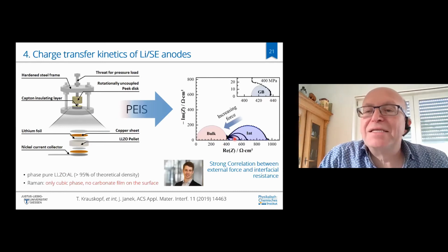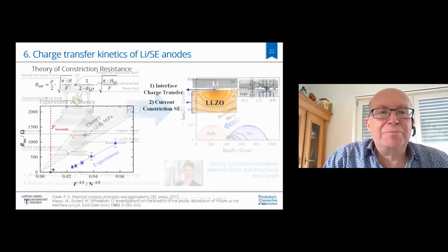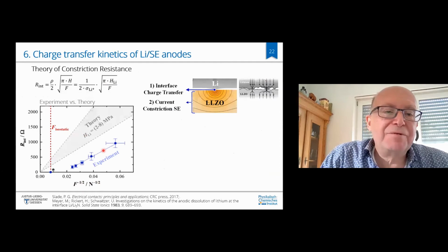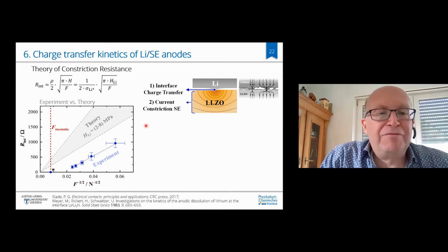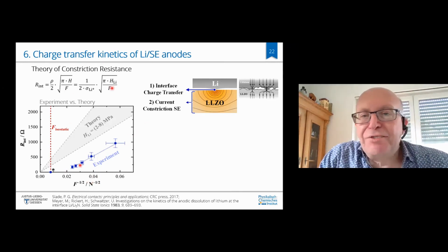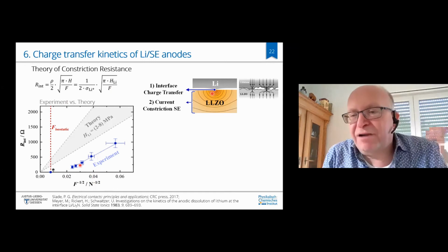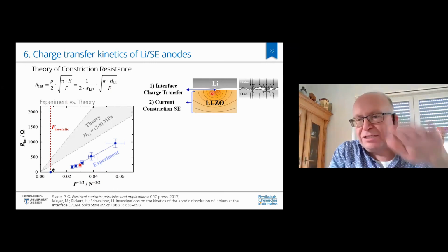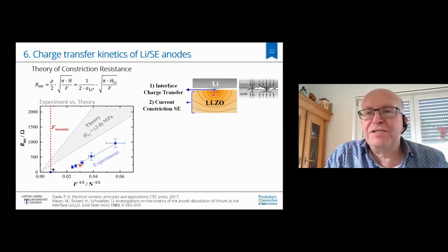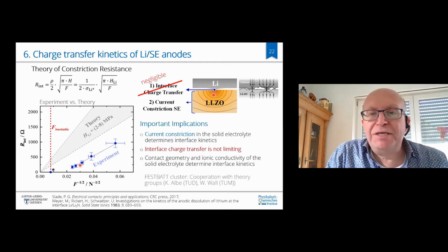And what you see here is that the impedance of the electrode interface with increasing force is going down and down. And what Torben quite nicely showed is that if you increase your force orthogonal to the interface, it follows a linear relation as a function of the inverse square root of force, which relates very nicely to the theory of constriction resistances and point contact. So if you have contact between just two materials that are rough, then you always have only a few point contacts, and each point contact is a constriction resistance. And if you increase pressure, then of course you increase the contact area, and that lowers the impedance.